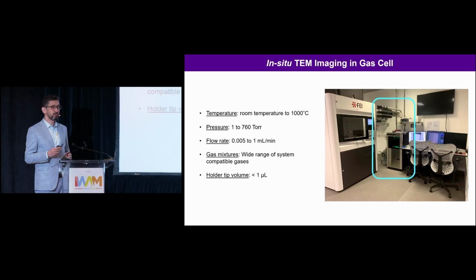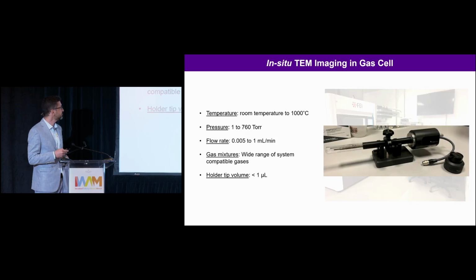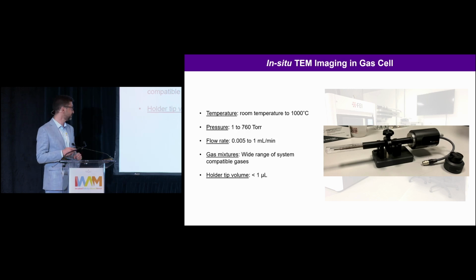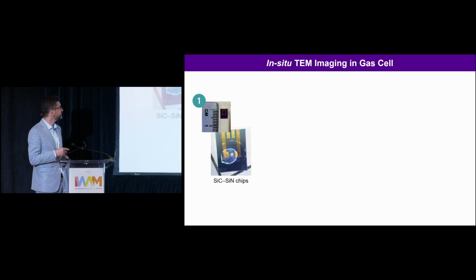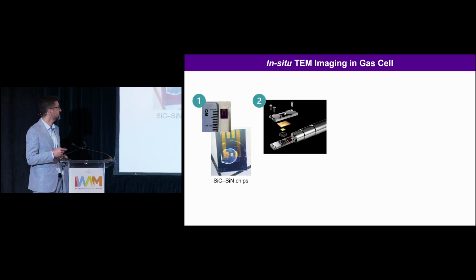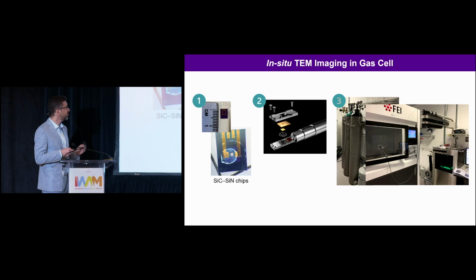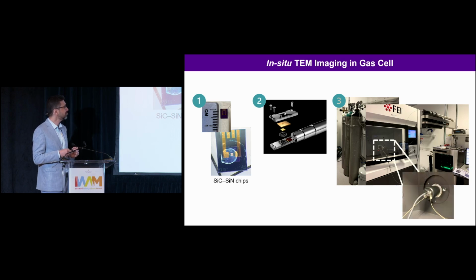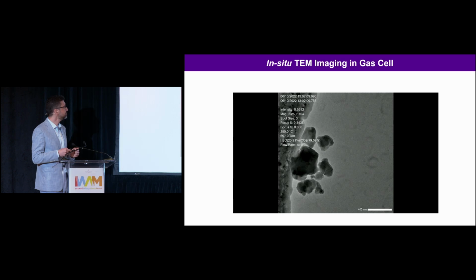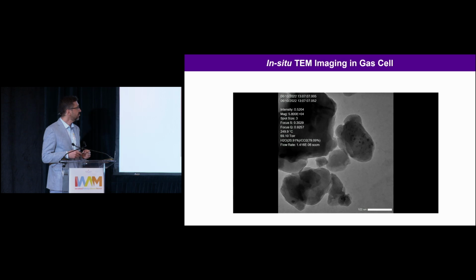And the special instrument that we use is an in situ carbonation chamber. In this chamber, we are able to vary the pressure, flow rate, temperature, and also gas mixtures, and use a tiny sample holder assembled into the TEM machine. Using silicon carbide and silicon nitride chips, we add our samples and assemble them into the TEM and look into the carbonation and hydration mechanisms in real time.